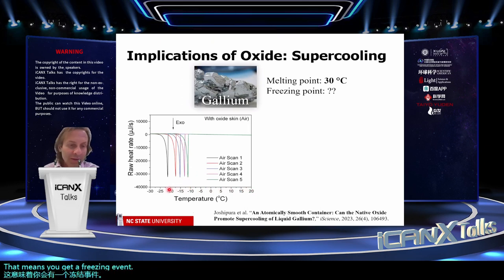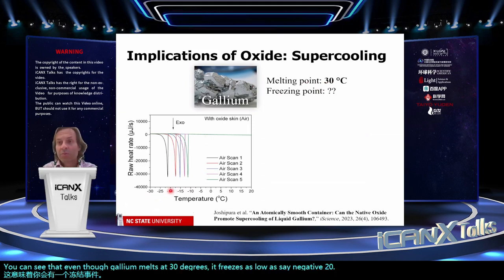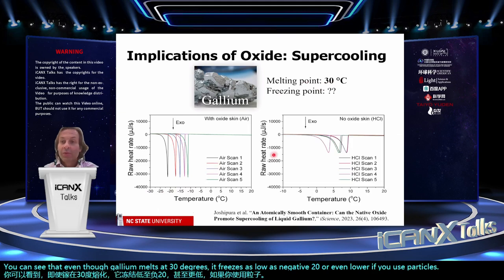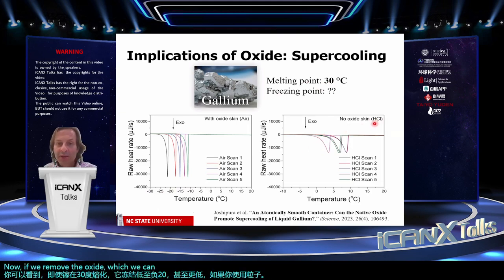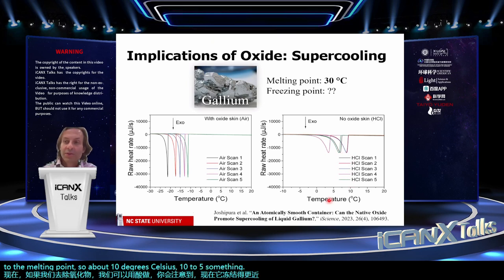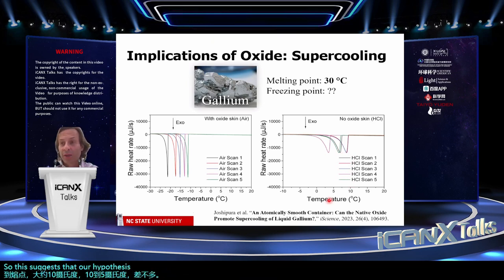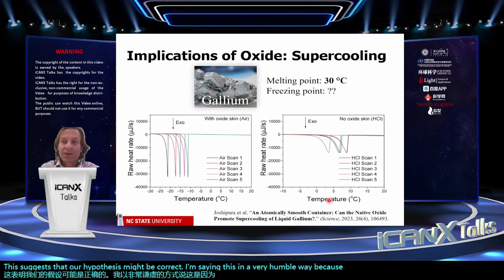So you can see that even though gallium melts at 30 degrees, it freezes as low as, say, negative 20, or even lower if you use particles. Now, if we remove the oxide, which we can do using acid, you'll notice that it now freezes closer to the melting point, about 10 to 5 degrees Celsius. So this suggests that our hypothesis might be correct. I'm saying this in a very humble way because this is some evidence, but this is really difficult to study.